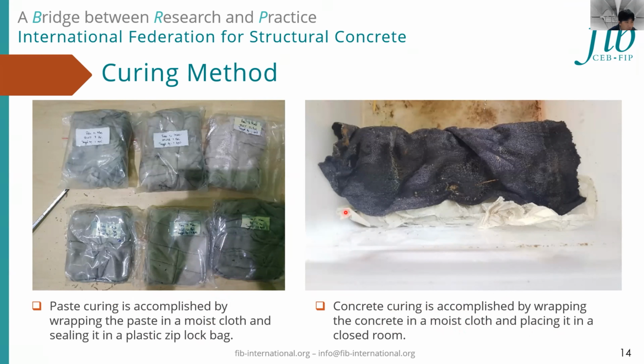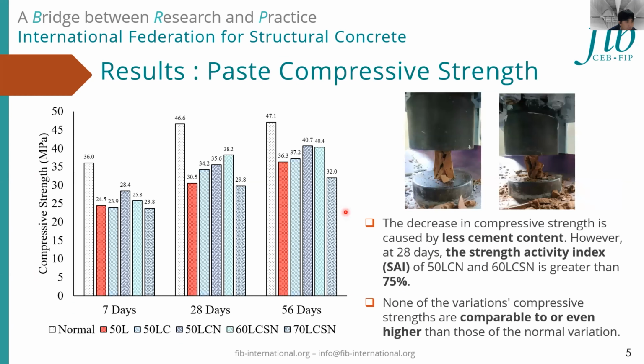Okay, then can you show me slide number 5 again? Like the strength development of each series. To me, it seems like for the series with LC replacement, the strength still keeps increasing even after 56 days, while the normal cement looks like it has a constant value after 28 days. But what if you measure 90 days or longer age for these kinds of specimens? Will they be similar to the OPC series?